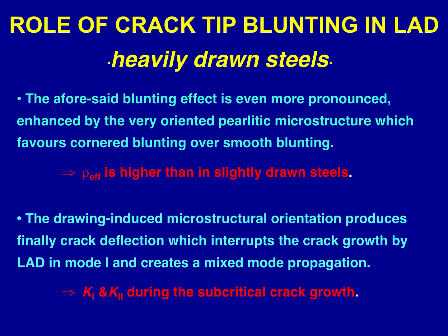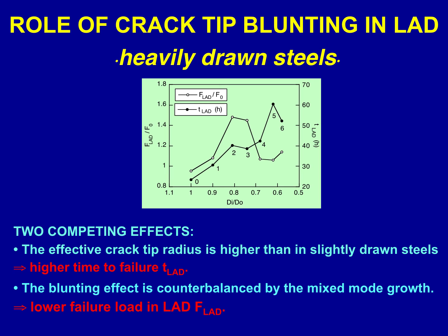The aforesaid blunting effect is even more pronounced in heavily drawn steels, enhanced by the very oriented pearlitic microstructure with cornered blunting over smooth blunting. Then the effective crack tip radius is higher than in slightly drawn steels. The drawing-induced microstructural orientation produces finally crack deflection, which interrupts the crack growth by localized anodic dissolution stress corrosion cracking in mode 1, and creates a mixed mode propagation, KI and KII, during the subcritical crack growth.